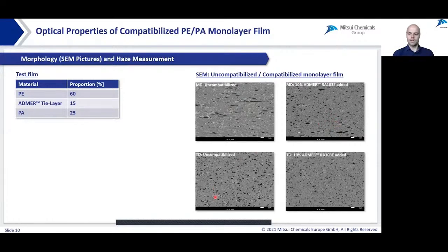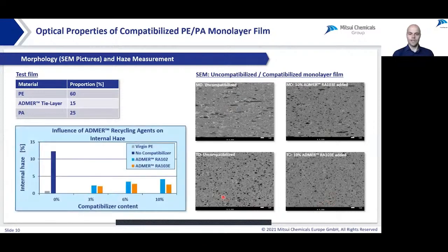Similar observations in transverse direction, comparing uncompatibilized and compatibilized samples. The SEM picture shows clearly a finer morphology by using ADMER RA103E. And the finer morphology results, as described before, in a film which is less hazy. Compared to the uncompatibilized sample, ADMER RA103E is reducing the internal haze and consequently increasing the transparency.